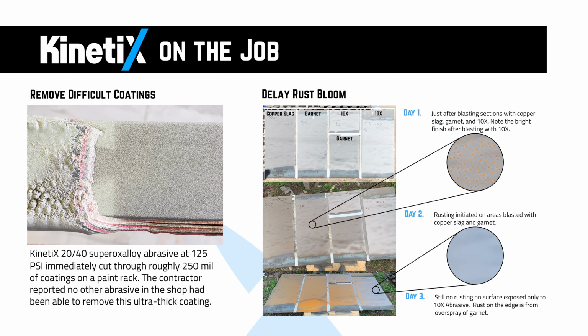On the right is where we began to understand how and why our abrasives delay rust bloom. The picture shows a 4x8 steel panel blasted in sections with copper slag, garnet, and KinetiX 10X. The objective was to compare speed and profile, but the panel was left in the yard. The owner of the yard noticed on day 2 that the copper slag and garnet sections had started rusting and the 10X section had not. It then rained overnight from day 2 to day 3, and there was still no sign of rust.